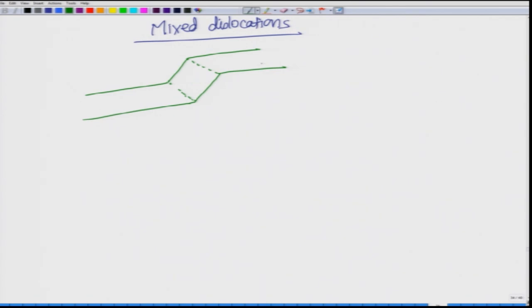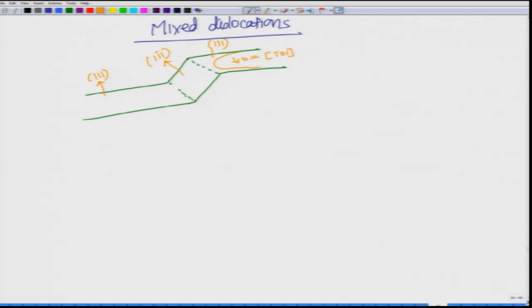When I draw a plane, do not think of it as a floor — it is an imaginary plane composed of atoms. Now let us look at a mixed dislocation. The Burgers vector here happens to be [1̄01], and this plane is (111). The dot product of [1̄01] with (111) is 0, so the Burgers vector is contained in this plane. The line vector here would also be [1̄01].